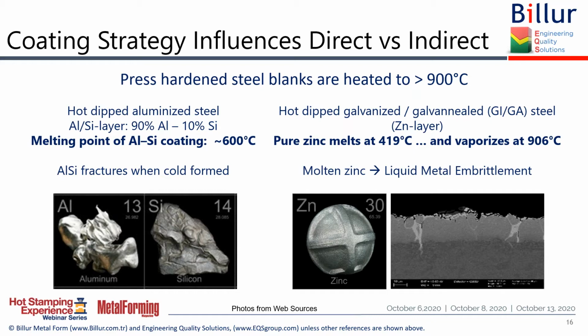That's number one problem. And number two problem, if I have liquid zinc and then form the part, I could have some micro cracks. By the way, I don't know if you can see my drawing here, but this is the zinc coating and this is the base metal. If I hot form while there's liquid zinc, that zinc could go inside the base metal and cause some micro cracks.